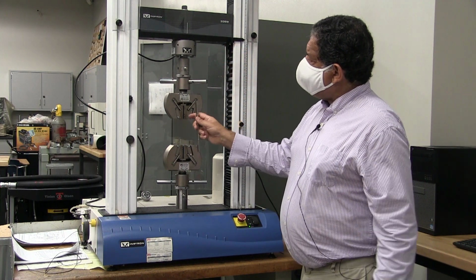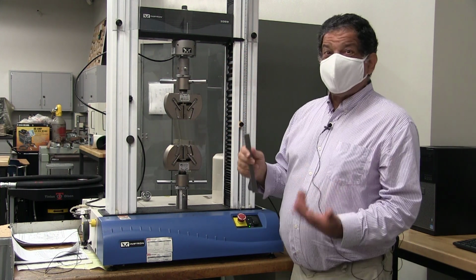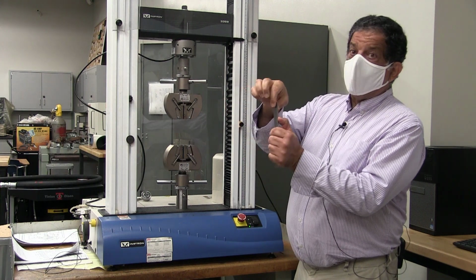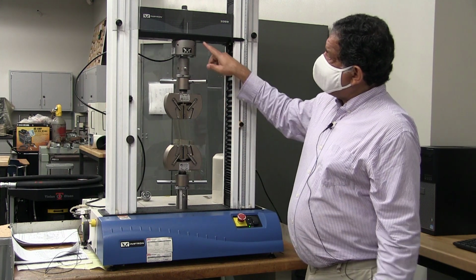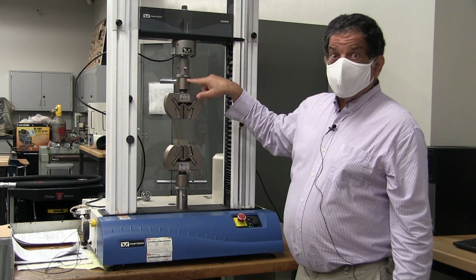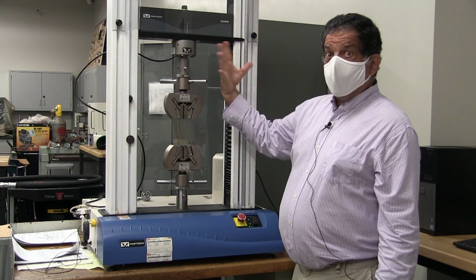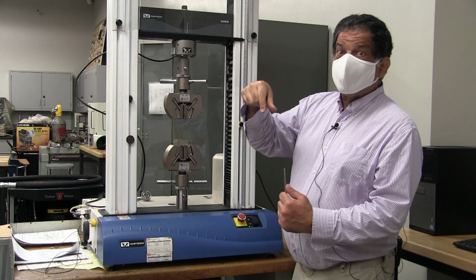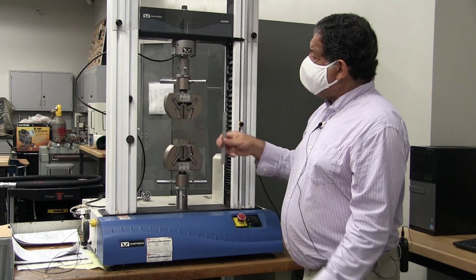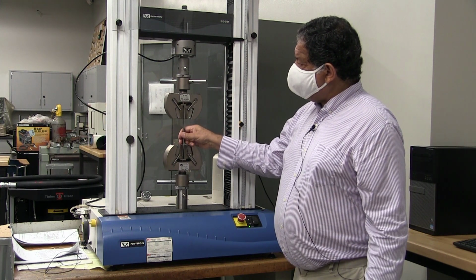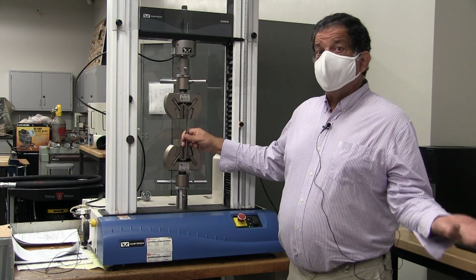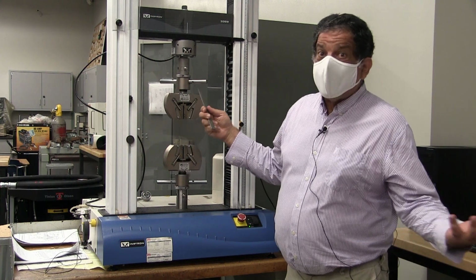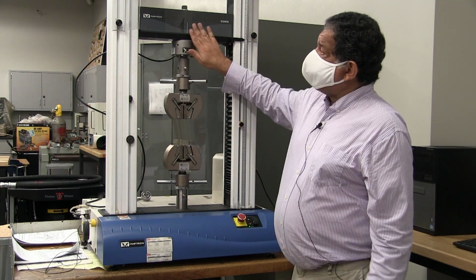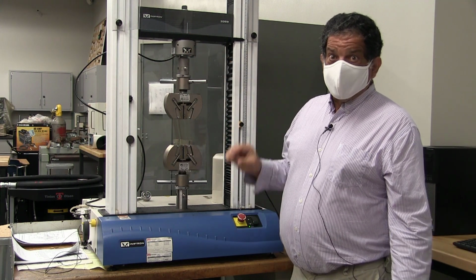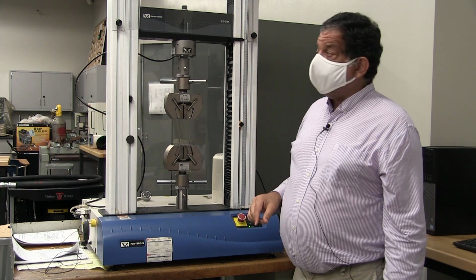But how far up the crosshead travels is not exactly the same as how far up the top of the specimen travels, because there's also some compliance in the load train. As I go up and the load builds up, this load train stretches a little bit too. So that's not a super accurate measurement of strain. As long as you're going to large strains, like the strain to failure, then this measurement of strain is fine, because the errors in it are fairly small.